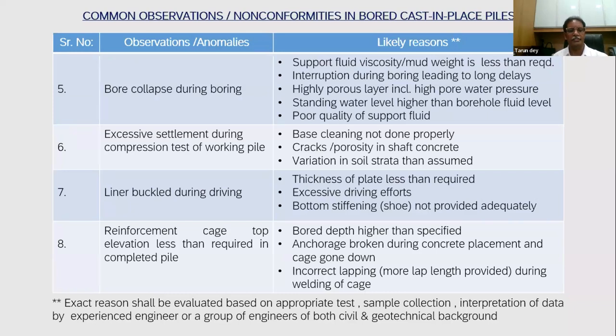So it gets distorted. So a little drivability analysis is required to be on the safe side. Sometimes we have seen the reinforcement cage top, after excavation, I find the elevation of the cage top is lower than required. That could be a problem on this higher bore depth. You have done higher than specified. It has gone down. Sometimes anchorage, we keep the cage hung on the casing.